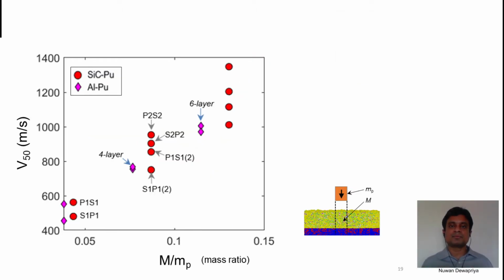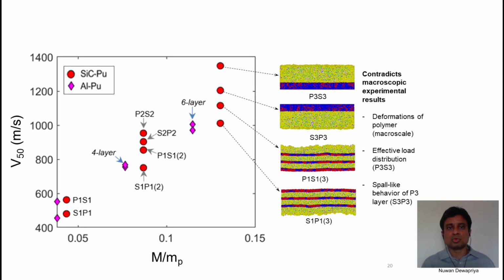Here V50s are plotted against the mass ratio, which is the mass of the target in the area directly underneath the projectile divided by the mass of the projectile. V50s of aluminum polyurea multilayers are also shown. One interesting observation is that having a polymer layer on the strike face is more effective than having it on the back face, which contradicts the macroscopic experimental observations. That can be due to different energy absorbing mechanisms at the two scales.